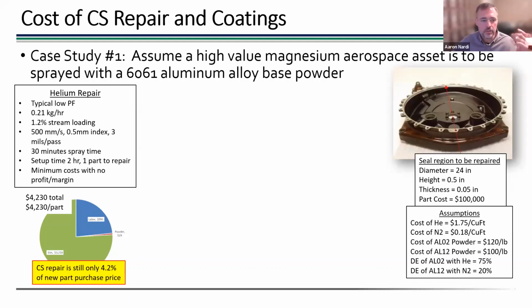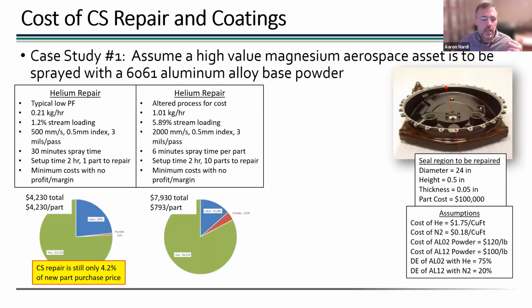If you did some modifications to that process, and this is where it becomes important to have that mechanism to be able to change your process around, you can increase your feed rate and increase your velocity so that you still get the same thickness per pass. And now you're getting down to about 6 minutes of spray time instead of 30 minutes.